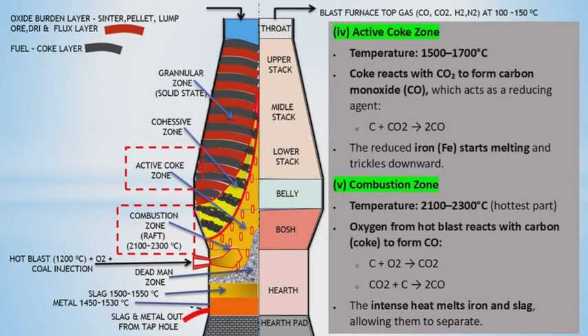Active coke zone. Temperature, 1500 to 1700 degrees Celsius. Coke reacts with carbon dioxide to form carbon monoxide, which acts as a reducing agent. C + CO2 = 2CO. The reduced iron starts melting and trickles downward.